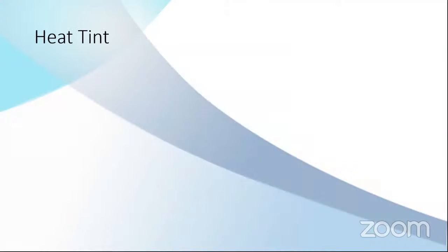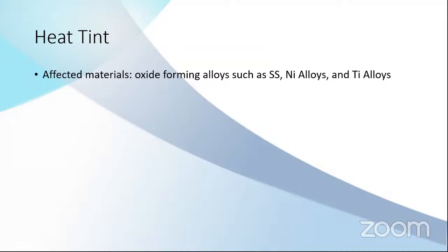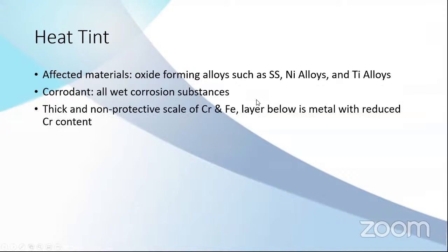Heat tinting. This also causes quite a lot of corrosion to stainless steel. We can often see this in the field. The affected materials are oxide forming alloys. So any materials that form oxide layers can have this heat tint problem: stainless steel, nickel alloys, titanium alloys. So when you have this heat tint, then all the corrosive products can corrode the material. So what is this heat tint?